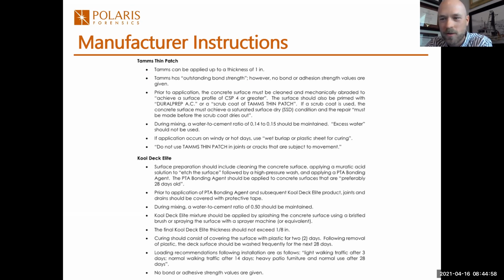The cool deck overlay was applied too thick. There was a lack of bonding agent between both the Tamms and the original deck, as well as the cool deck and the Tamms. There was a lack of surface roughening. Existing expansion joints were covered, which is a big no-no. These materials were loaded at very early ages, which again is a no-no. There was elevated water content in both of these materials, and there was a lack of curing. And we were able to support these conclusions based on the testing and the test results and the test data.